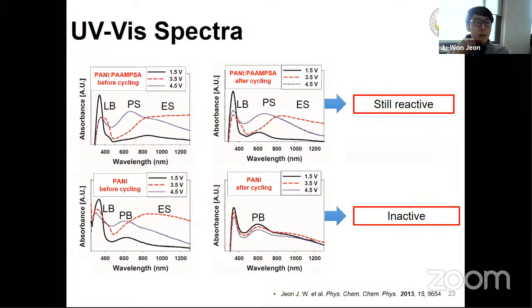So in order to find the reason why we have the very high electrochemical stability for the PANI:PAAMPSA, we performed UV spectroscopy for the PANI:PAAMPSA and polyaniline homopolymer before and after the cycling. Before cycling, the PANI:PAAMPSA can exist in the LB, ES, and PS form, depending on the electrochemical voltage applied. But after the cycling, it can also show the reversible behavior. It exists as ES, PS, and LB, depending on the electrochemical potential, which means even after cycling, this PANI:PAAMPSA is still reactive. But in the case of the polyaniline homopolymer, you can change its oxidation state before the cycling, but after the cycling, it just exists in the polyaniline base form instead of changing its oxidation state, which means this polyaniline is not active anymore.